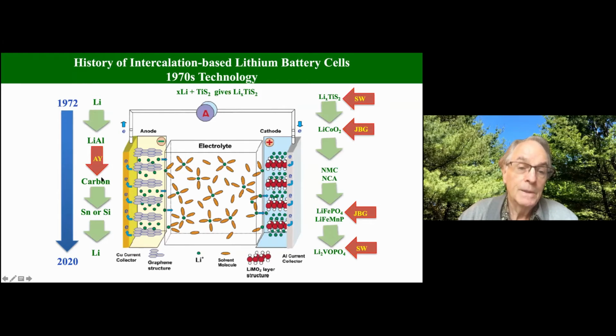Akira went to carbon. Carbon takes up half the volume of the cell, and you need 72 grams of carbon to store 7 grams of lithium. So if you want to increase the energy density, you have to get rid of the carbon eventually. A lot of work on tin or silicon. There's challenges there. Tin will cycle at 99.95 coulombic efficiency. Silicon isn't close to that at the moment. And the real push is now it's gone full circle, and people are now working on lithium again.